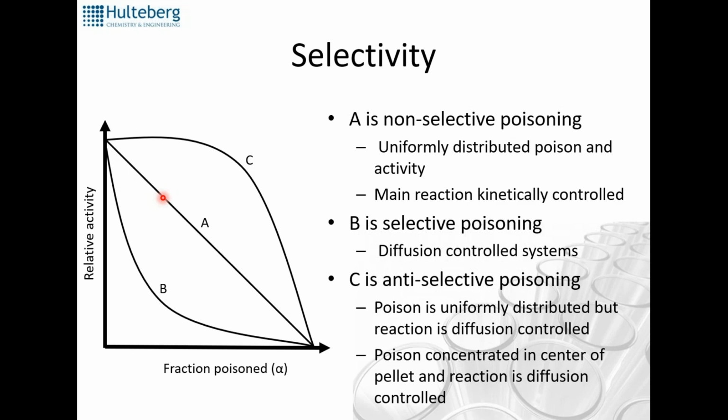If you have mass transfer limited type reaction, you can also see the inverse, where you have much more deactivation for a little introduced poison, and that's typical when you have diffusion control systems to get this behavior. So basically, when a little poisoning on the outer will do a lot of damage because of the reaction regimes with respect to diffusion.